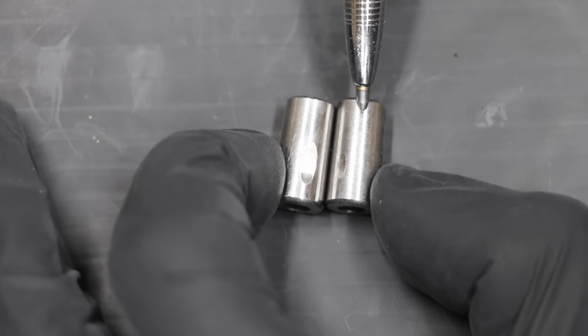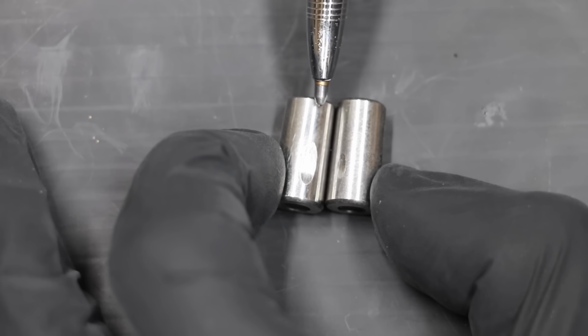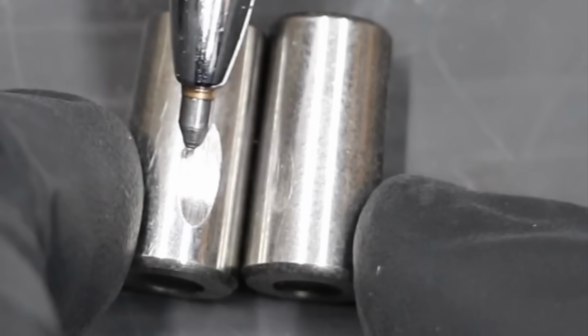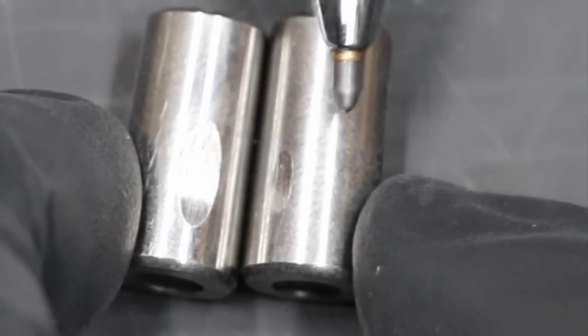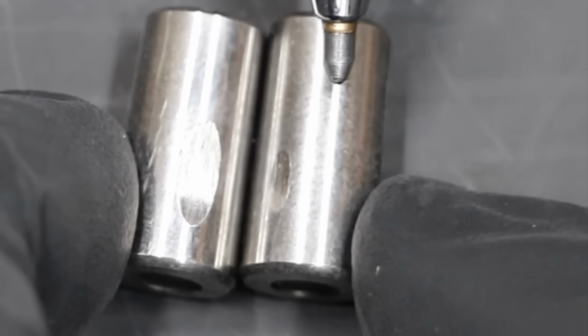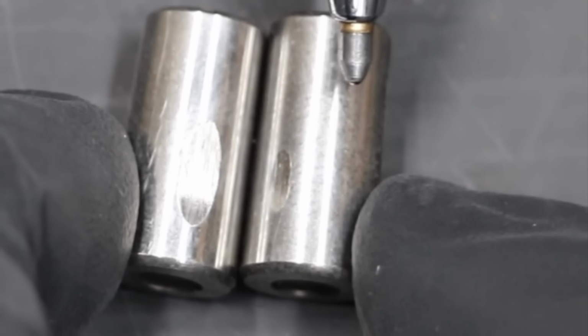Supertech is on the left and Lucas is on the right. I really did not think we'd see such a huge difference between the two brands. Now, in fairness, Supertech claims to be a light-duty grease. Obviously, the wear scar is huge on this bearing compared to the Lucas, which has a very small wear scar, indicating that it has terrific film strength.